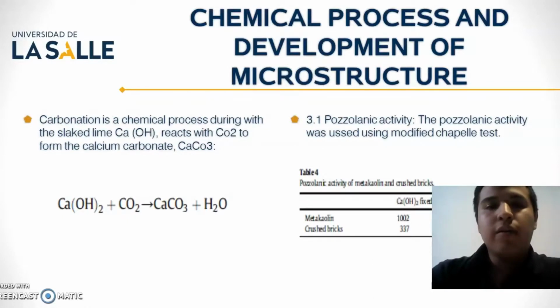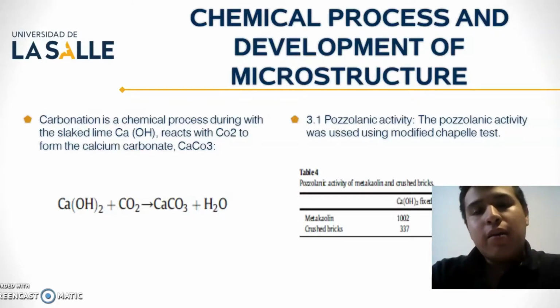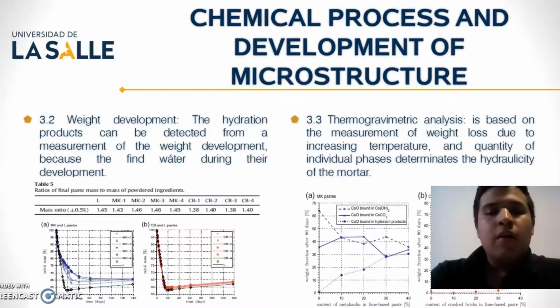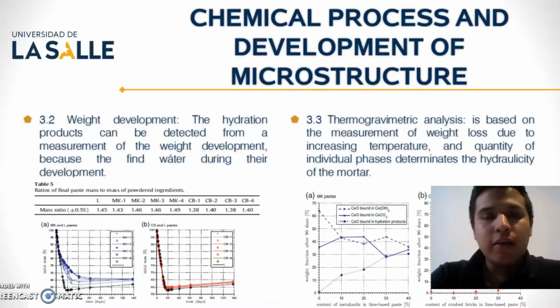The pozzolanic activity was assessed using the modified Chapelle test. This method is based on the reactivity of the test material, in our case the crushed brick or metakaolin, with calcium oxide provided by calcination in water. The addition of metakaolin resulted in a quite significant reduction of weight loss at early age. This water retention wasn't observed in the paste containing crushed brick, indicating a weak pozzolanic reaction.